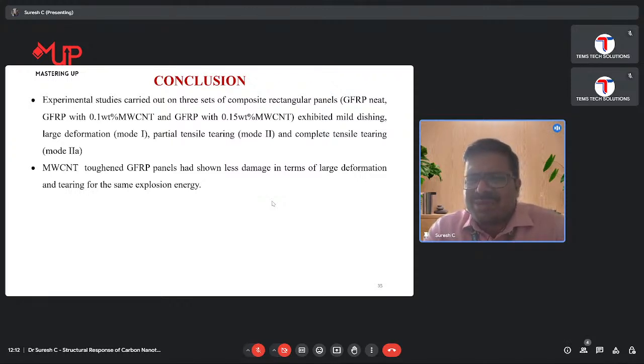We have studied how the deformation, tearing, and the complete damage is taking place using the software and compared with the experimental studies. So it gives us confidence that we are able to create the same as the experimental studies, and we have done it for different charge weights, even for 150-gram charge weights, and for different thicknesses of plates. We have increased the plate thickness, and behind the plate we kept water at one-fourth, one-half, three-fourths, and completely filled, and we have studied all those things.